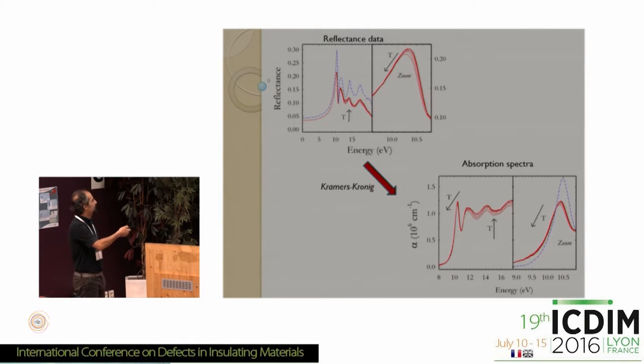Now, the absorption spectrum of amorphous silica looks like this. Again, you have a strong increase around 9 to 10 electron volts, which tells you that you are going beyond the fundamental edge, and then you have a series of peaks. Let us focus our attention on the first peak, around 10 electron volts, which is this one, and you have a zoom of this peak on the right panel. This peak is slightly different when you go from the crystalline, blue, to the amorphous version of SiO2, but it's present in both. This was already known before our studies, of course. This is due to the formation of an exciton. In other words, this is the first excitonic peak of SiO2, and it peaks more or less at 10.4 eV.